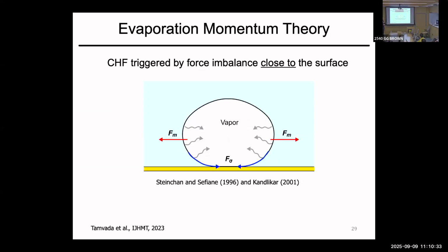But fast forward to 1996, the Sefiane group in Europe came up with a different explanation. They said, you know what? If I have a bubble forming, we see bubble formation even up to 95% of the critical heat flux. They said that basically this vapor-generated interface is pushing the liquid back, right? And the surface tension wants to bring the interface back. So it's a fight between the two. If you get to such a temperature that the evaporation rate is very significant, then the momentum generated is such that the contact line, what wets the surface, cannot come back. And so they call it the evaporation momentum theory.